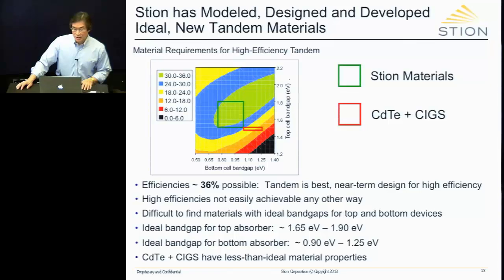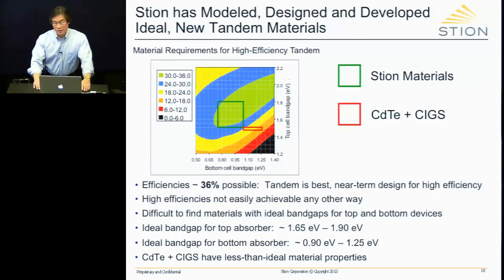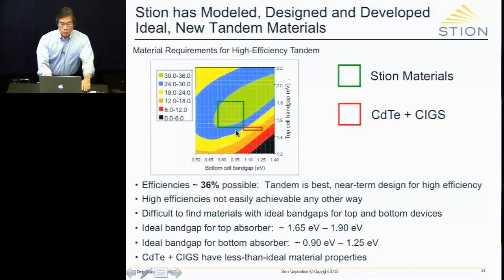Japan and other Asian countries have outlawed cadmium, and it's a big problem. So just to give you, if I had my druthers, I'd work with Telluride. But nevertheless, for a tandem device, it sits right here. What we've been able to do using chalcopyrites is tune the lower band gap within this region and tune the top band gap from here all the way up to here. But I've only circled around where the green region is. So we can tune it within precisely this region. And therefore, that's why we feel that we get to very high efficiencies with our tandem.